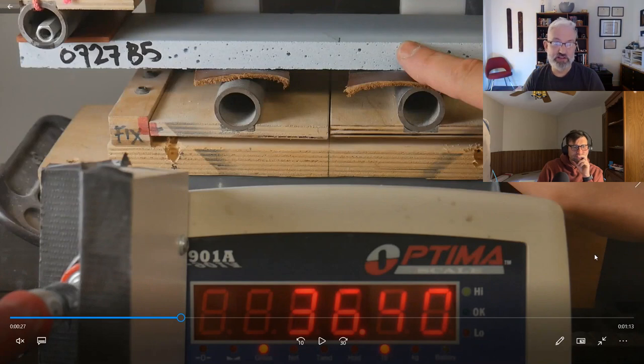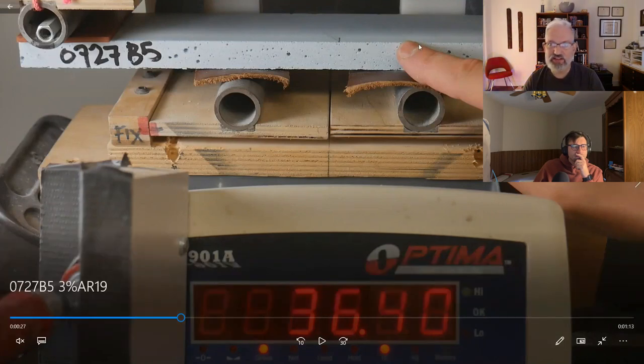Now, this is a thinner sample, and I'm zoomed in a little closer, so again, the numbers are different. You can't compare. The other one broke at 35, and this one had first crack at 36. But even if they were identical, this gets its first crack that's maybe visible. Can you see that?